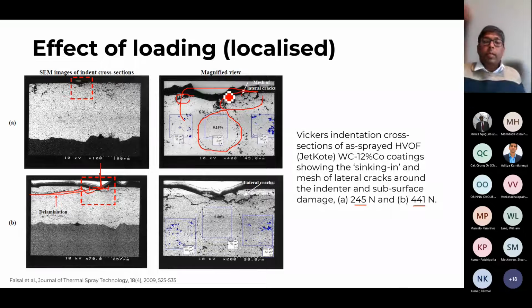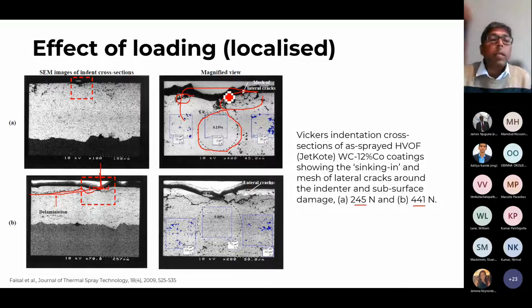And you may feel from the surface, oh, it is only local fracture happening, but after removal, it has penetrated deep and laterally. So you may find cracks appearing very far off. So any little contact or debris going in, in static and dynamic conditions, will degrade the surface significantly. And if you do it over a period of time, then that is how the coating will degrade. So this can be your catalyst layer, electrode layer.